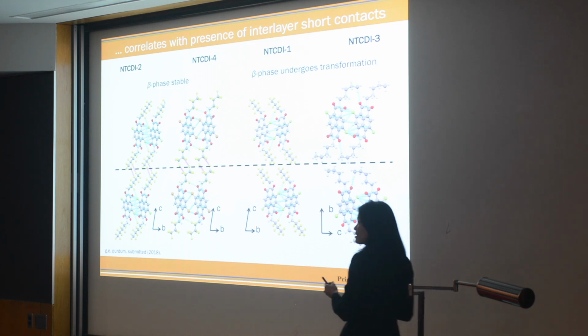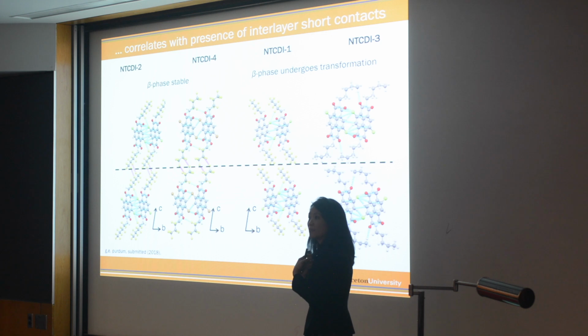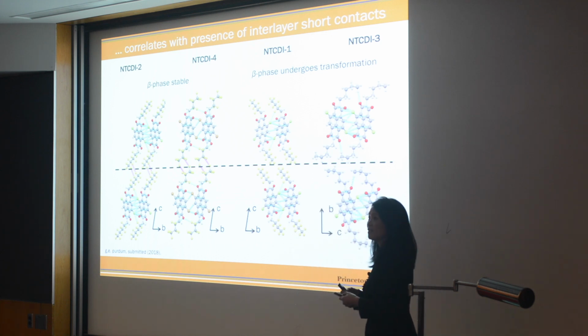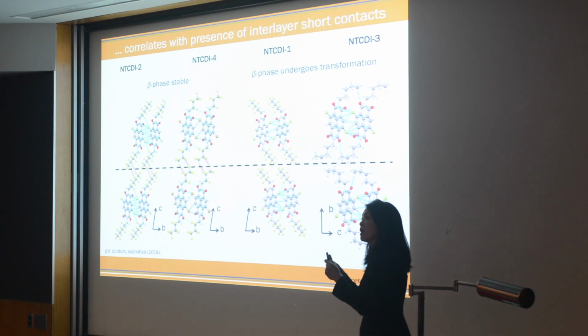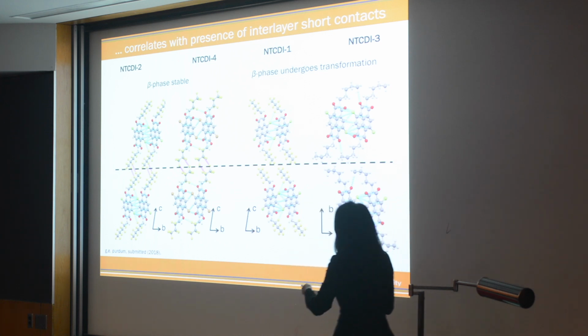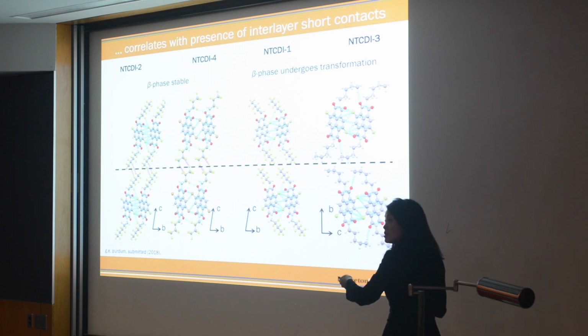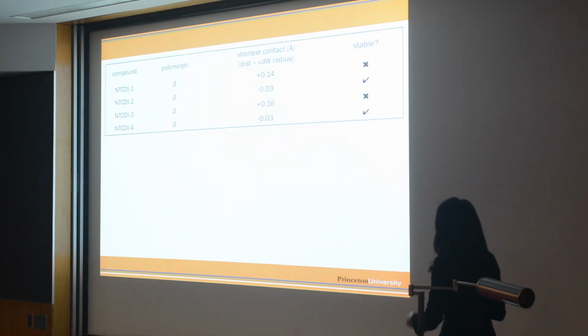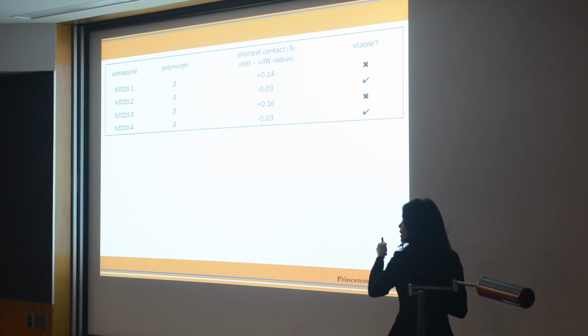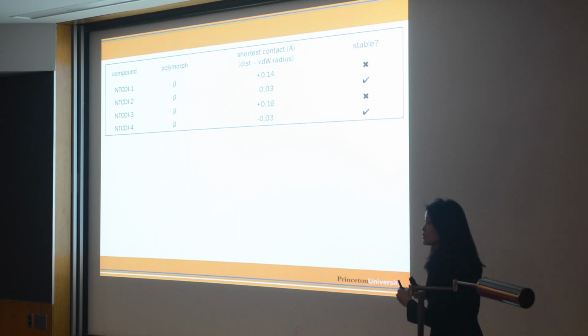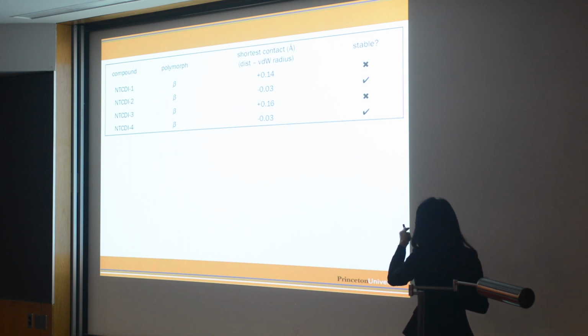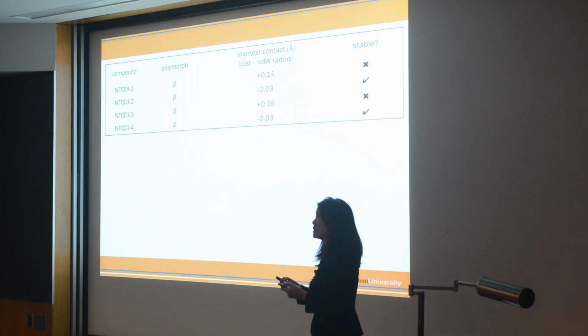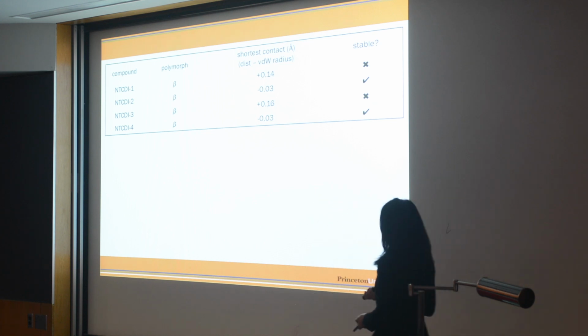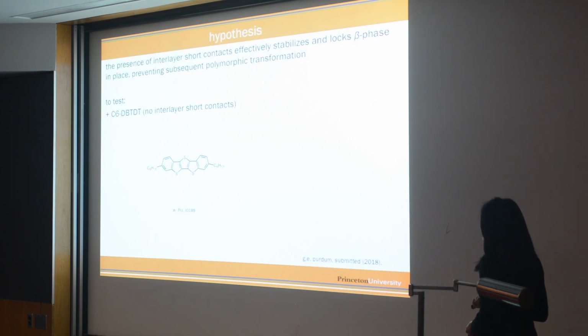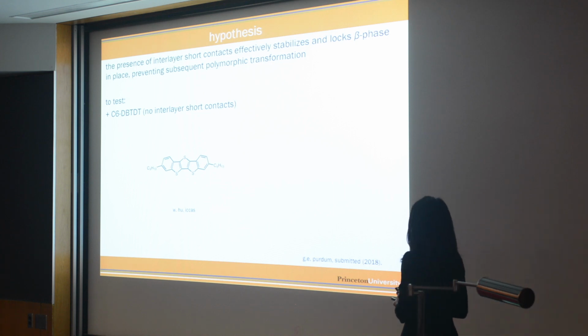So if that number is positive, that means there's no short contact by our definition. And if that number is negative, that means there are short interlayer contacts, because that distance is smaller than the sum of van der Waals radii. So by that definition, the numbers here should be negative, and the number here should be positive. Okay, and we can calculate that. And this is what our observation is, right? Beta phase is not stable for NTCDI 1 and 3 because we can transform out of it. But the beta phase is stable for NTCDI 2 and 4 because it appears that we're kinetically trapped in those two polymorphs.